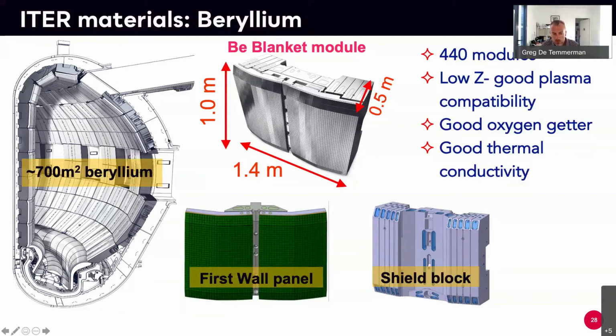down neutrons. Remember that you have a plasma at 150 million degrees here in the center of the machine, and about 2.45 meters away, you have a magnetic coil, which is cooled at 4 degrees Kelvin to be superconducting. So you have extremely high temperature gradient, and you should avoid any neutrons actually going into the coils, because that will heat them and they will not be superconducting anymore.